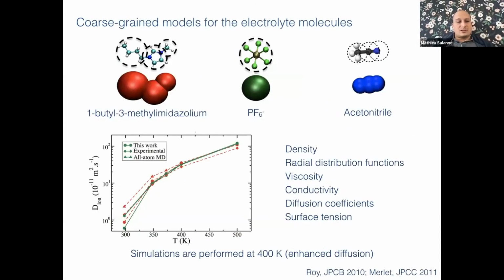So this is now changing because our code is more efficient, but all the results I will show you are based on older results, in which we had to simplify the liquid a bit because otherwise the simulations were too long. So we used some coarse-grained models, which means that instead of having all the atoms, we were, for example, representing the PF6 anion with only one sphere. So this is a simplified representation, but we used force fields that allowed us to represent very well most of the physical quantities that are known for this liquid. So even if it's not atomically accurate, it's at least accurate for transport and thermodynamics.